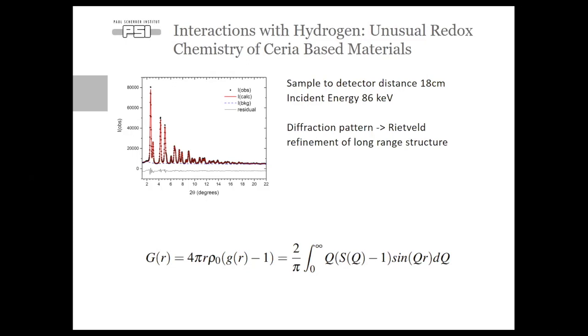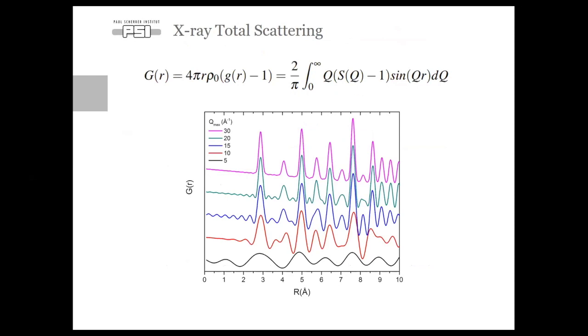An alternative method here is actually just to take the Fourier transform of the normalized scattering function, and this leads to the G of R, the pair distribution function. And when we look at this equation, we can see something which is fairly inherent to this technique. We need a very high Q range. So here I have simulated the effect of the Q max of the integration, Fourier transformation, for simulated FCC lattice. It becomes pretty evident that we need measurements in excess of 20 angstrom inverse are required to get an accurate PDF. Below this, artifacts in the PDF appear due to the Fourier transform truncation. Obviously, high Q, the better that's possible. However, in time-resolved measurements, often we are limited due to statistics at high Q.